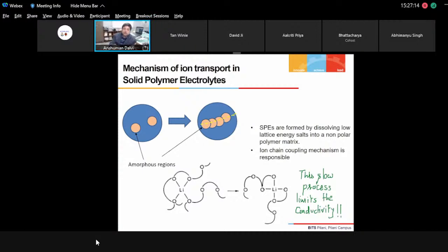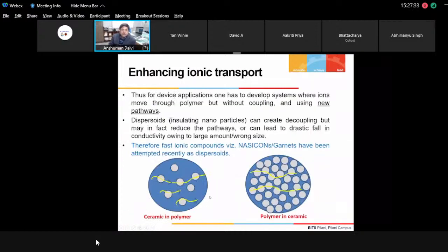And if you see the NASICON kind of materials, inside there is a three-dimensional structured array, possible pathways for the ions, but then at the grain boundaries electrical transport is hampered. So to look for a combination of these two, one talks about a hybrid where we think about dispersing the NASICONs inside the polymer matrix. Long back people dispersed insulating particles inside the polymer matrix to enhance the conductivity, and there could be an order of magnitude or a little more enhancement in the conductivity, but it was finally limited because of the size and shape of the insulating nanoparticles and the amount of nanoparticles also.